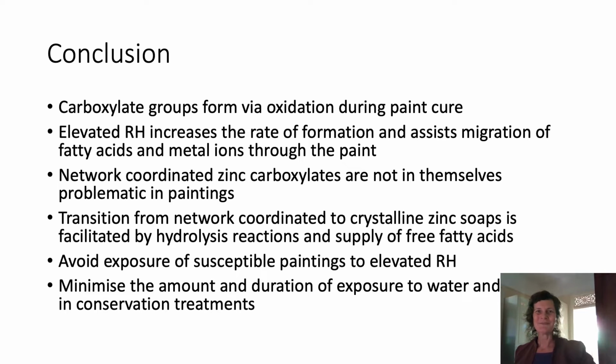So to conclude, current modelling on zinc soap formation in oil-based paintings shows the development of carboxylate groups during the early stages of paint cure and during subsequent ageing is a critical stage in the process. The presence of water accelerates both the formation of carboxylate groups and the migration of acid and metal ions through the paint.